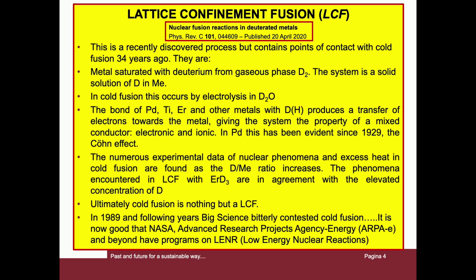This is a recently discovered process but contains points of contact with the cold fusion of 34 years ago. They are metals saturated with deuterium from the gaseous phase of deuterium. The system is a solid solution of deuterium in metal. In cold fusion, this occurs by electrolysis in heavy water. The bond of palladium, titanium, erbium, and other metals with deuterium and hydrogen produces a transfer of electrons toward the metal, giving the system the property of a mixed conductor, electronic and ionic. In palladium, this has been evident since 1929 with the Coehn effect. The numerous experimental data of nuclear phenomena and excess heat in cold fusion are found as the deuterium-metal ratio increases.